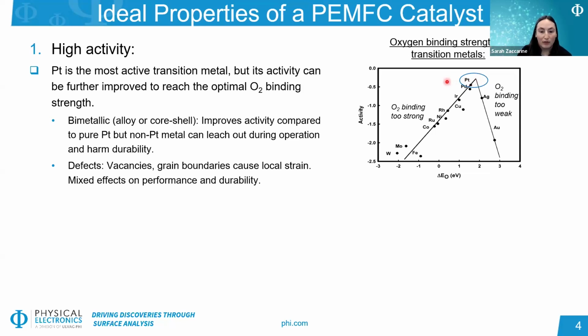So we can optimize the performance of the platinum slightly more by doing a few different things. And one of the ways to do that is to create an alloy with a different metal or a core shell structure. So this will use slightly less platinum, but it will also improve the activity of the platinum itself because it will alter the platinum d band. And there's a variety of metals that you can use as the secondary alloy material. However, sometimes this other transition metal can leach out of the catalyst during operation of the fuel cell, and it can contaminate the cell and harm long-term performance.